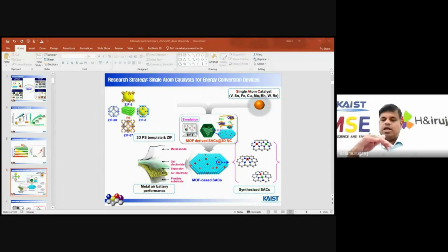When we use a basic electrolyte, we have to use the upper-side first-row transition materials like vanadium, iron, copper, molybdenum, nickel, or cobalt. Based on the application, we have to choose the first-, second-, or third-row materials. After that, we fabricate the materials, and we confirm the fabricated material by DFT, density functional theory calculations. From the density functional theory calculations, we can find the optimal catalyst. The optimal catalyst, meaning the free energy close to zero, is a better catalyst, from the PDOS. We also do the ORR and OER performance DFT calculations.